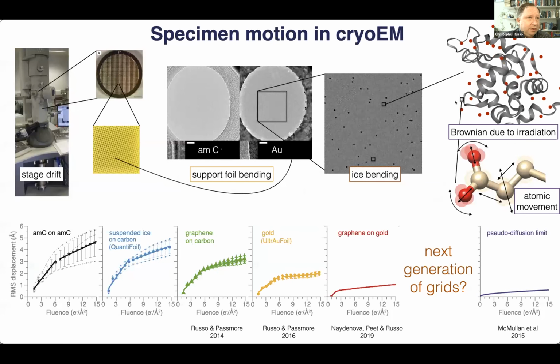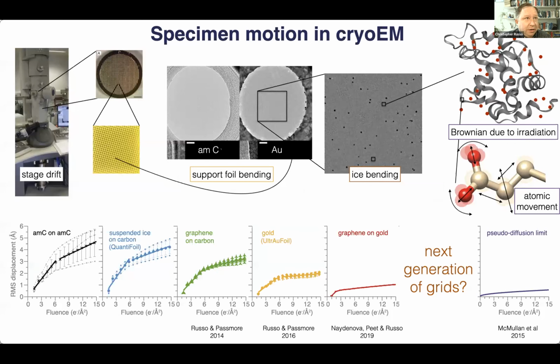And then if you were to go even further in looking at movement in the specimen, you reach the point at which the water molecules are actually moving during irradiation in the beam. And this was worked out as well by Greg McMullan in about 2015. And it turns out that they're not moving too much. They're moving about an angstrom per electron per angstrom squared.